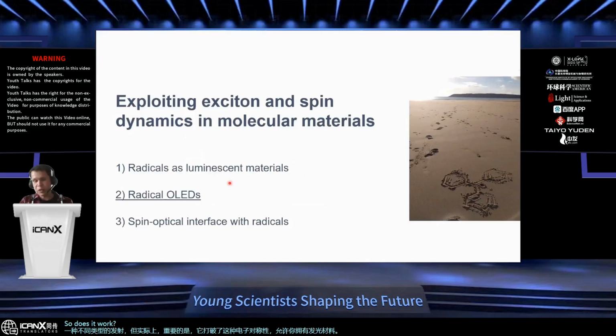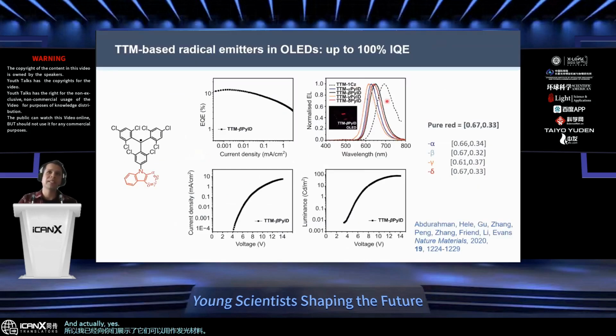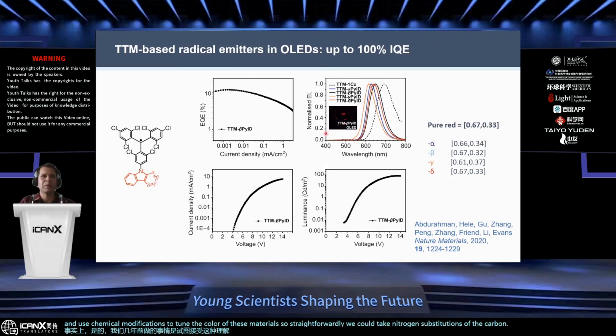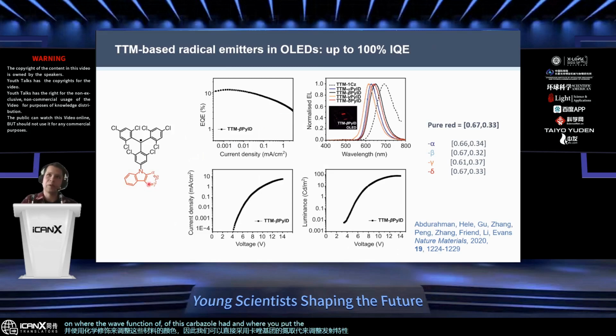So does it work in a useful way for devices? That's what I want to tell you about next. So I've shown you that they can be used as luminescent materials. And something that we did a few years ago was to try to take this understanding and use chemical modifications to tune the color of these materials. Straightforwardly, we could take nitrogen substitutions of the carbazole group to tune the emission properties a bit. Depending on where the wave function of this carbazole was and where you put the electronegative group, you could tune your emission. And we could match very well the coordinates that you need for a red device.